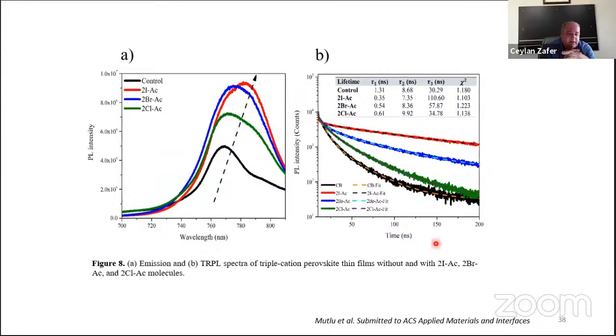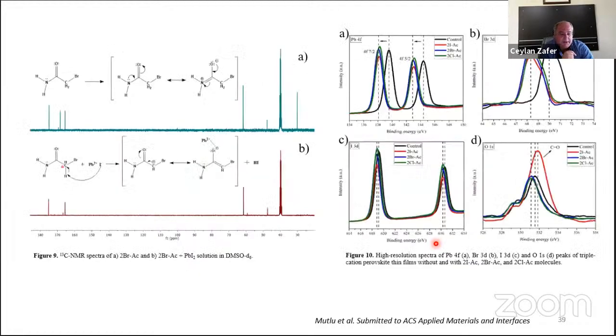We check again the photoluminescence and the lifetimes of the photoluminescence spectra, and we got similar results with bromoacetamide, like benzyl bromide, compared with the previous work. This is really interesting because both solvents produce hydrogen bromide, and the hydrogen bromide interacts with the lead iodide perovskite. We checked this reaction under NMR conditions, and in the molecular manner we observe a conversion of the bromoacetamide, and it makes a reaction with the lead ion over the oxygen.